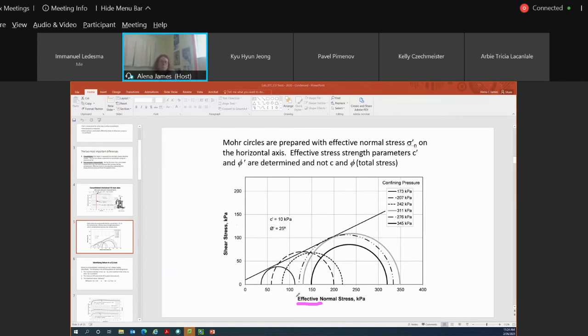The reason why the term shear stress doesn't have effective in front of it is because shear stress is equal to sigma 1 minus sigma 3. So if we were to calculate effective, it would be sigma 1 minus u, minus sigma 3 minus u, all in brackets. But you'll see here this minus minus becomes a plus u. So the pore water pressures actually balance each other out. So it really is just simply sigma 1 minus sigma 3, which is simply your shear stress. So that's the reason why shear stress doesn't have the word effective in front of it. But normal stress is required to have the word effective in front of it.